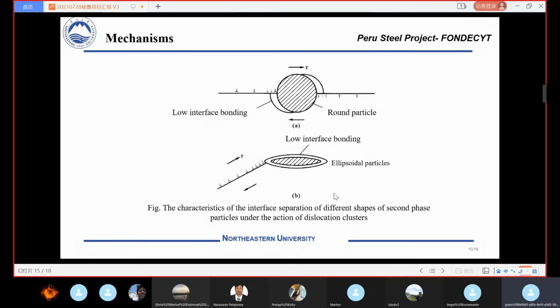Here shows the mechanisms for crack formation. The uniformly distributed second phase can lower the crack initiation possibilities. However, it will promote the initiation with increasing particle size, and it is related to the particle shape. Here this figure shows the interface debonding around two different particles.